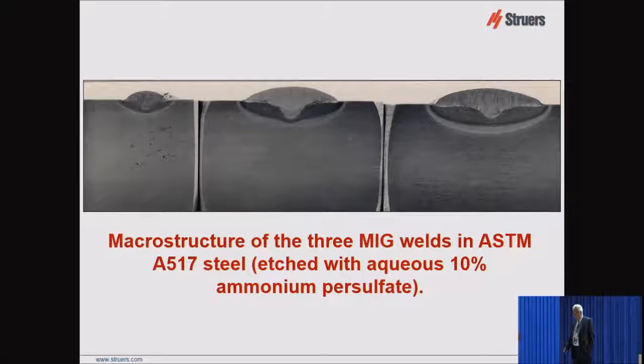The heat affected zone here is much deeper. The weld is much larger. There's this middle deeper penetration. This has a very deep penetration right here, and it looks like there's some cracks right in here. And this one is much smaller. But again, that angle there is a little bit steep, which is not a good thing.